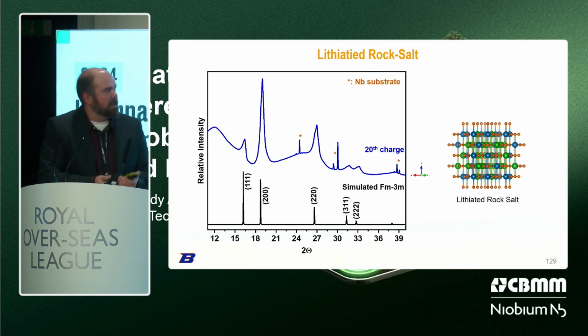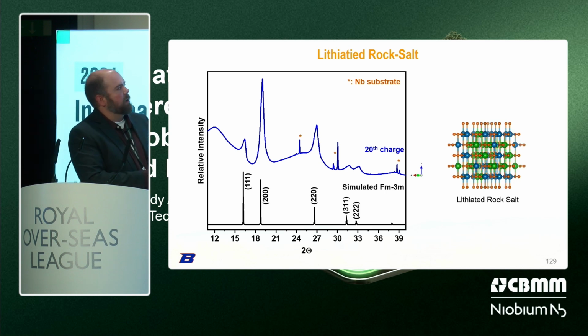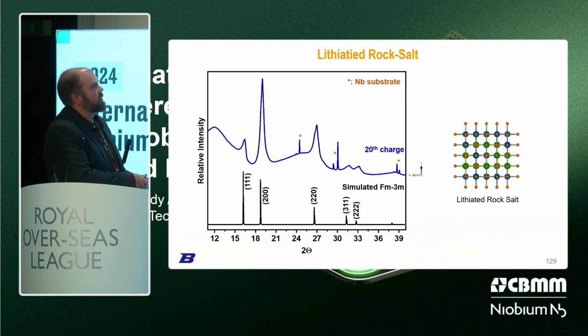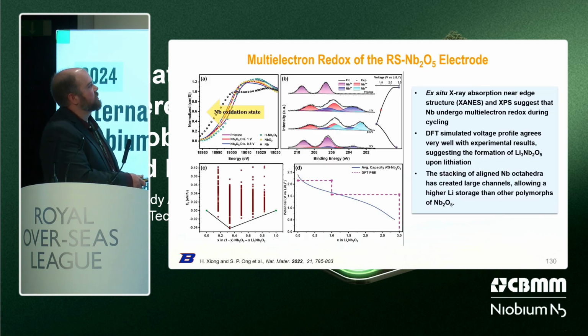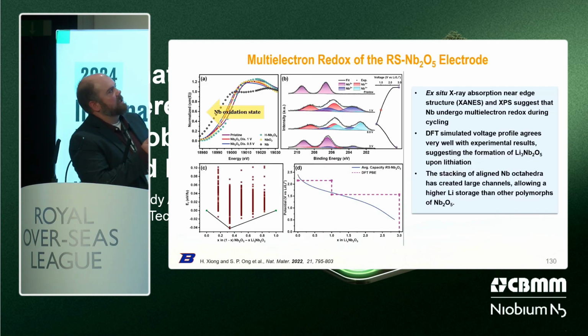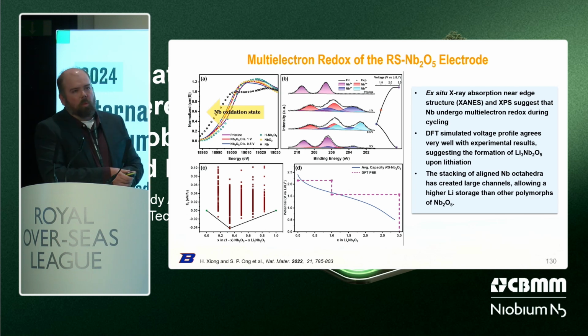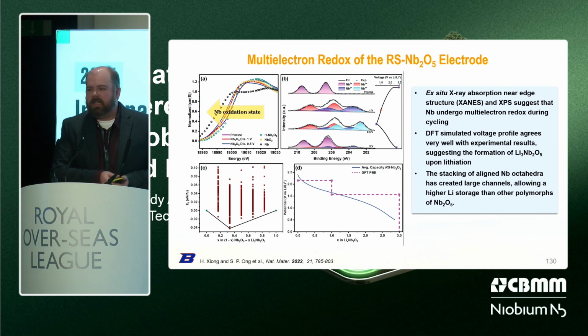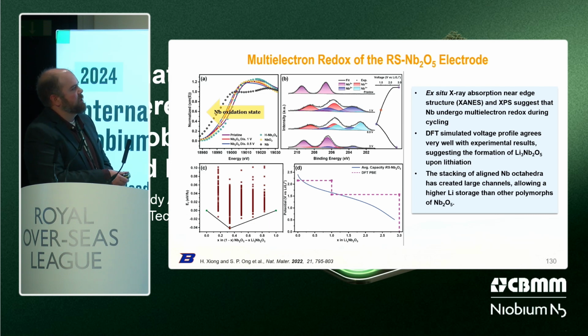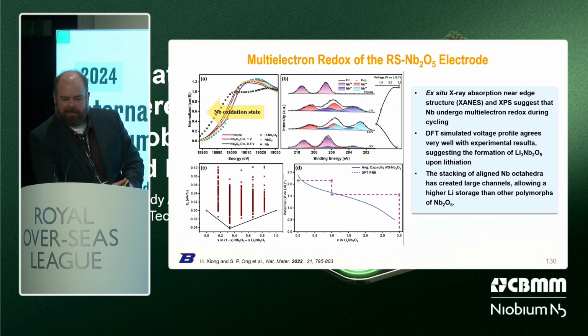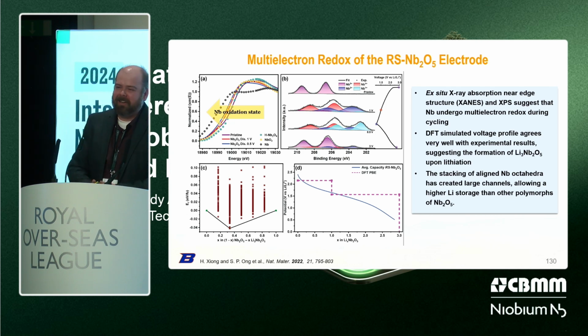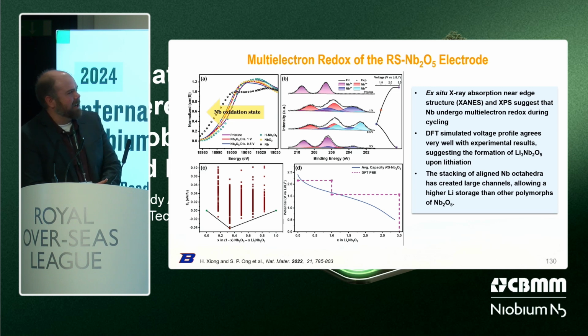So we now have this idea of a lithiated rock salt structure, and how it was developed from cycling, using an electrochemical method to develop a new crystalline structure. And now we wanted to test, okay, at this point we're like, wow, we're getting a lot of capacity out of the niobium oxides. Why should we only be getting theoretically 202? I went to Claire and said, I'm getting over theoretical capacity. Claire was skeptical, I would say. So we had to do a lot of work to see whether this was really what was happening.